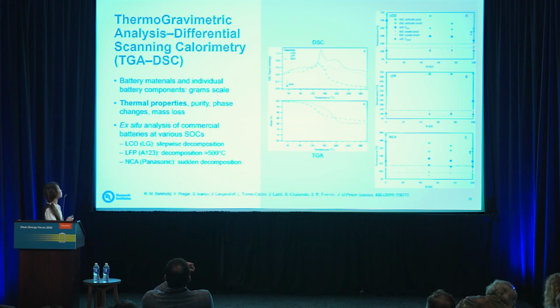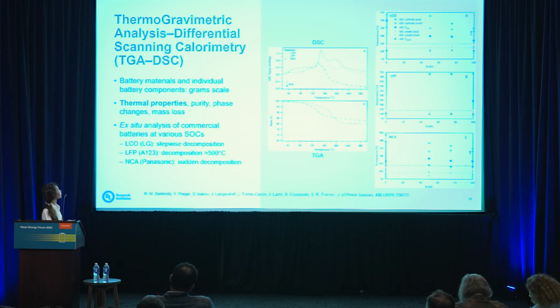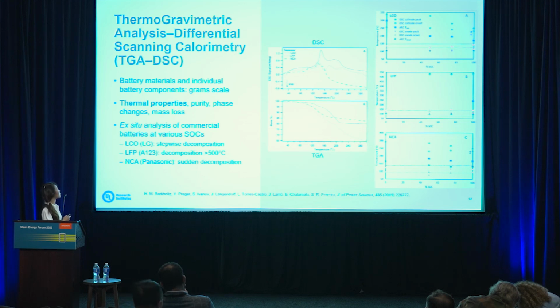Something else that we're interested in is thermal properties. We can use thermogravimetric analysis, TGA, with differential scanning calorimetry, DSC, to find out more information. This is a gram-scale instrumentation method and can provide information for the different battery materials or different components. Other than thermal properties, we can understand the purity of the phases, any phase change, and any mass loss. On the right here, this is the data obtained from this paper. They did an ex situ analysis of commercial batteries at various SOCs. They looked at different chemistries: LCO, LFP, and NCA.